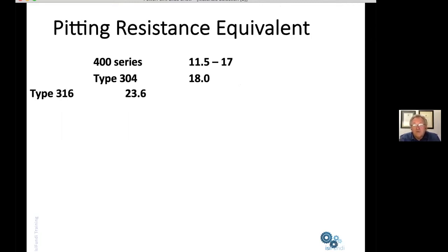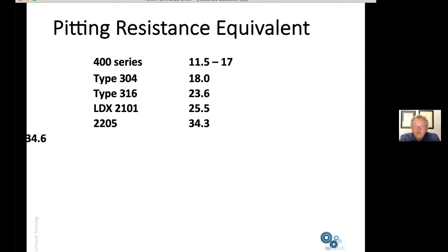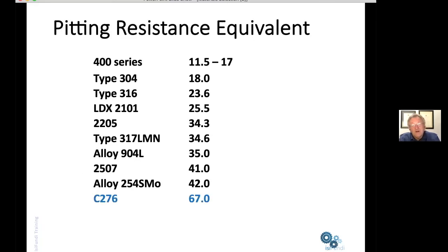If we have a look at these various materials that we've been talking about, you can see that as you go up the alloy tree, you get higher and higher pitting resistance equivalent numbers, which means that these effectively are materials that are more and more resistant to corrosion. Right down at the bottom, you can see there the number C276, with a significantly greater pitting resistance number. This actually goes beyond the realm of stainless steels and is one of the Hastelloy materials, which is more of a nickel alloy than a stainless steel per se.